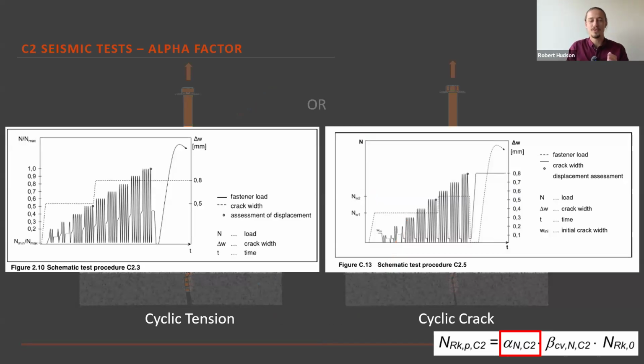Now, to give you a sense of scale of the impacts of these two tests, this will vary quite significantly depending on the type of anchor you're using. Some anchors are quite resilient to some of these mechanisms, others are less resilient. But it would not be unusual to expect a reduction factor from the cyclic tension test in the range of about 0.9, so maybe a 10% reduction in capacity. And the reduction factors that I might expect if I was testing an anchor and putting it through the cyclic crack test would be in the range of 0.2 to 0.3, which is a 70 to 80% reduction in anchor capacity.